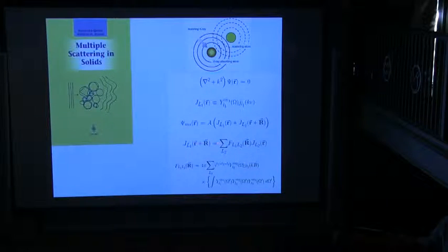We can project a spherical wave from one center onto the other, and the coefficients that enter are the Bessel functions involving the separation between the two atoms. This red term here is the origin of all those EXAFS oscillations.